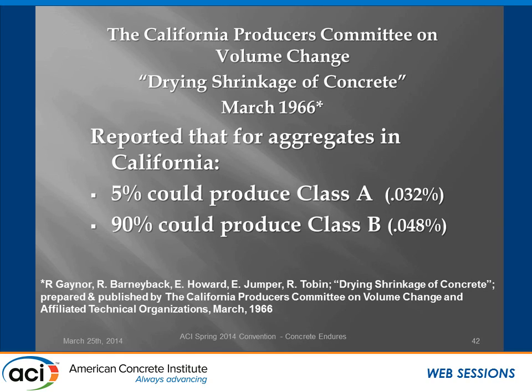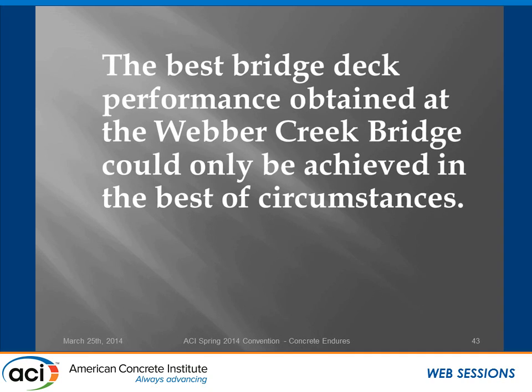Simultaneously, the California Producers Committee on Volume Change in March 1966 reported that for aggregates in California, 5% of them could produce class A concrete, and 90% were in that class B range. So this is why we're beating our head against the wall on these bridge decks. The best bridge deck performance obtained at Weber Creek can only be accomplished in the best of circumstances, and there was no way around it at the time.